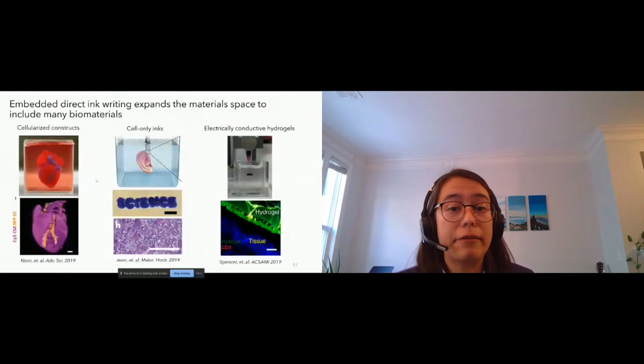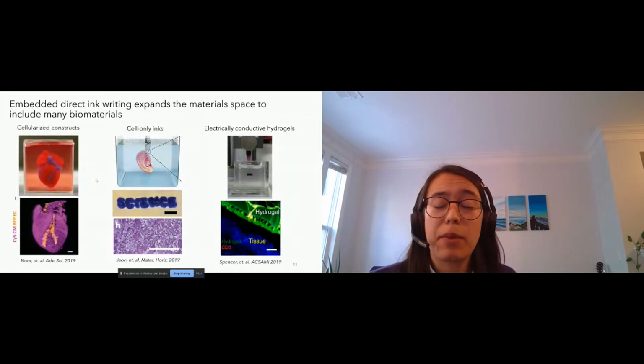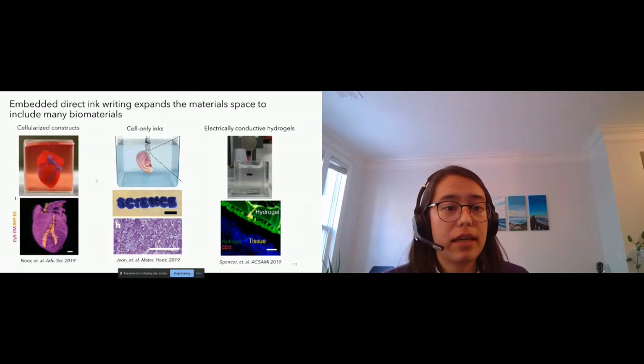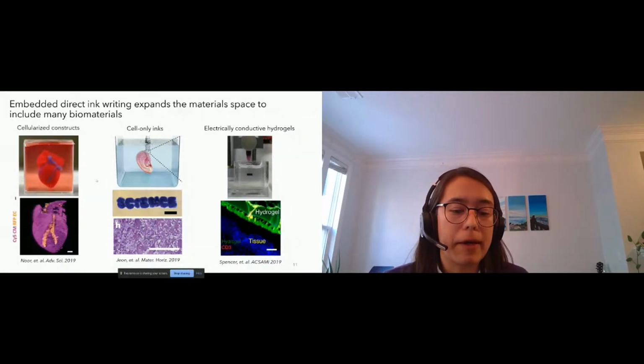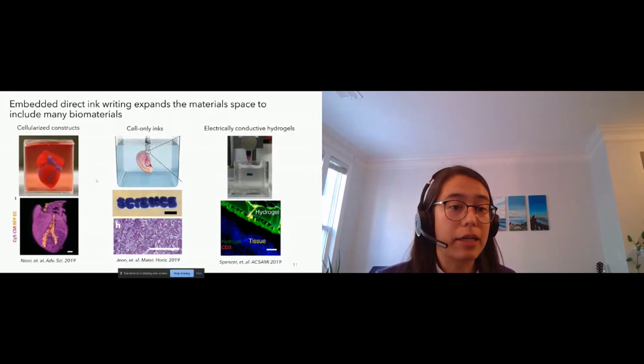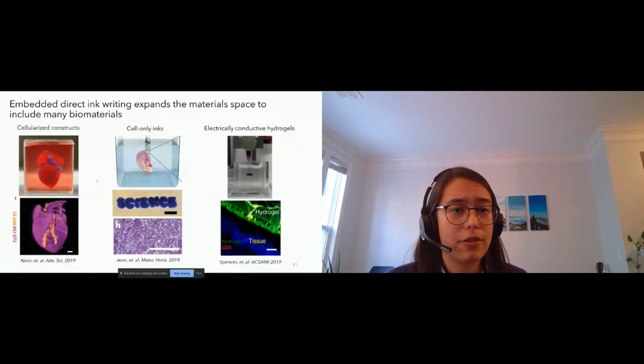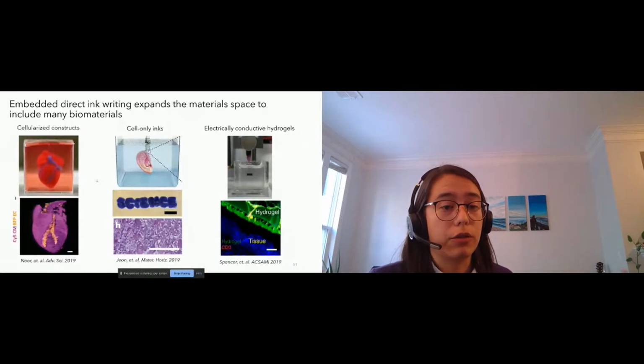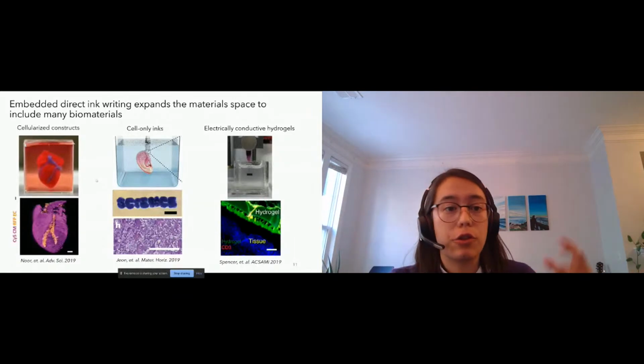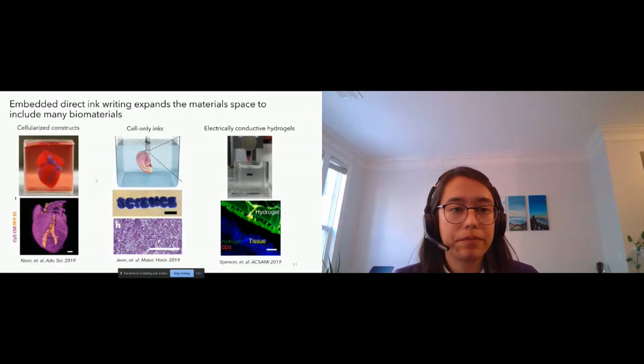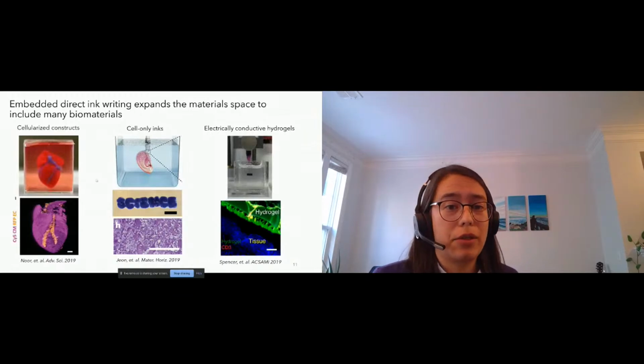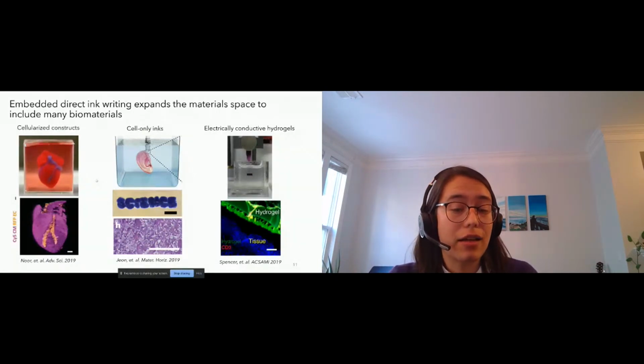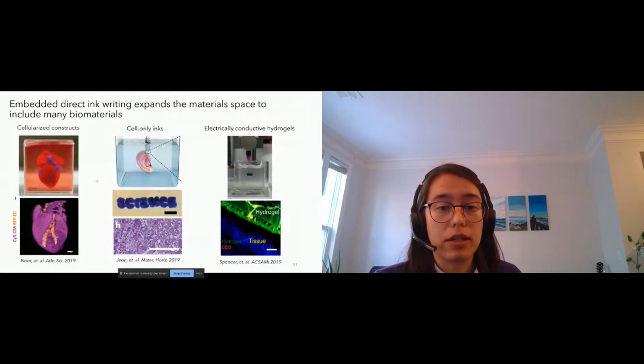People have been able to print a wide variety of materials using this technique before, and it's been particularly useful for bioprinting. You might have seen this paper a couple of years ago where they printed a heart, which actually included human heart cells, as well as some extracellular matrix. So you can print these cellularized constructs and actually use the bath to support the growth of that construct by introducing nutrients that will feed the cells and allow them to proliferate. People have also been able to print cell-only inks. Instead of having all these biopolymers available to scaffold the ink, they can print just cells, and those cells have been able to grow and develop tissues.